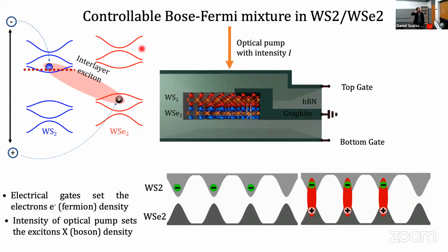So the way to do it is we excite out of resonance optically. Then this creates a plasma of electrons and holes. They will decay non-radiatively, bind together, and form interlayer exciton. And we can then achieve, depending on the intensity of the pump, situations in which we populate the material only with excitons. But because of their nature, we are then controlling the bosonic population in the system. So we can have two independent parameters on the fermionic and bosonic populations, and that's the physics we are exploring here.